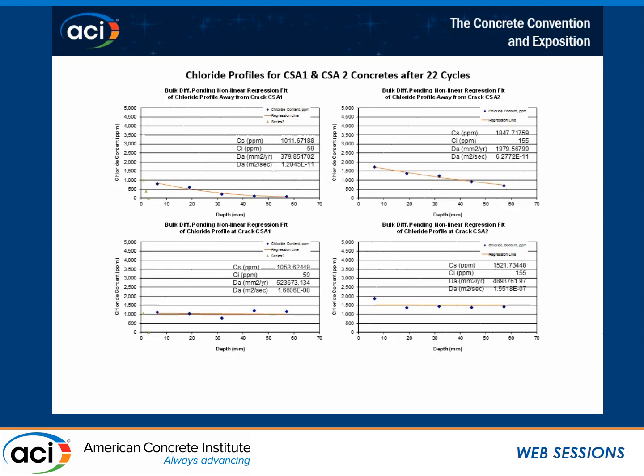So it does matter what cement you're using, because in OPC you still decrease the chloride coming in as you go over the crack, and in some of these particular alternative cements, these two ones, there was no reduction in chloride from the surface going down to beyond where the bar was.